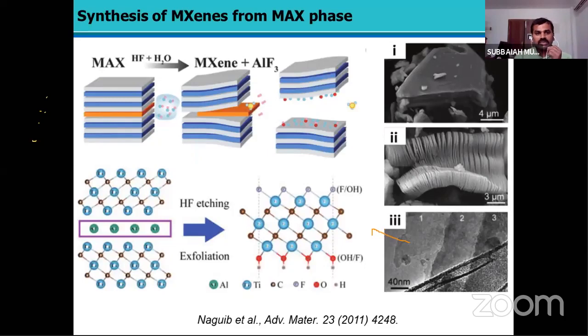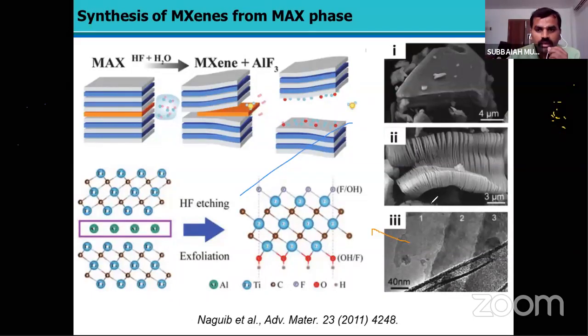Then this is the schematic representation of the MXene phase derived from the MAX phase. It was selectively removed, and you can see it in the bottom image. The HF selectively etched, and new functional groups like fluoride and hydroxide were introduced on the surface of MXene, which is highly useful and induces the hydrophilic nature. You can see some images of MAX and MXene, and it was confirmed by TEM image also.